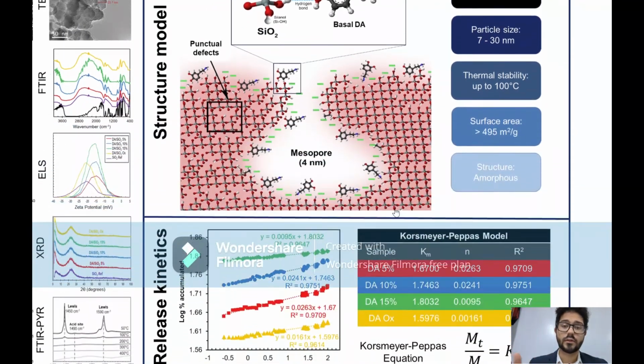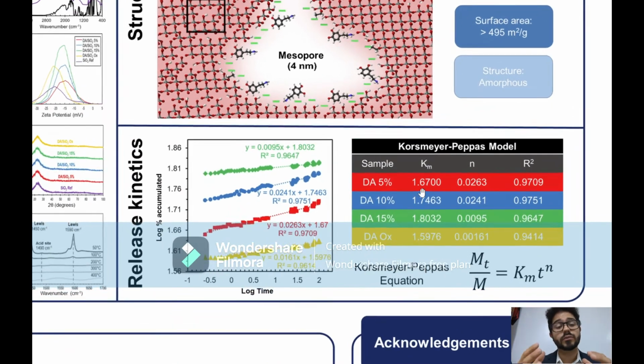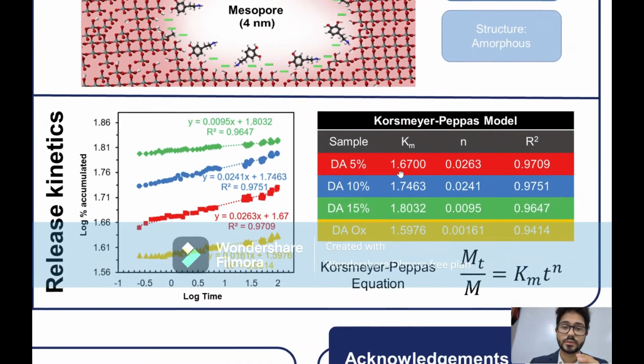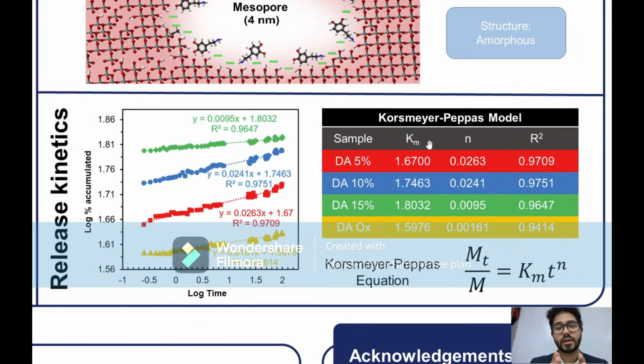Thus, when evaluating the release kinetics, we were able to observe that the model that best described it was the Korsmeyer-Peppas model, which describes the release in polymeric systems, as in the case of amorphous silicon dioxide. As you can see here, the value of n of the Korsmeyer-Peppas equation for our nanoreservoirs was less than 0.5 for all samples, indicating that kinetics are governed by diffusivity, particularly a Fick diffusion.